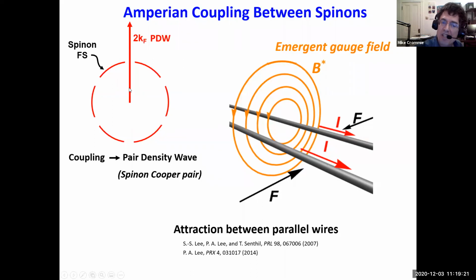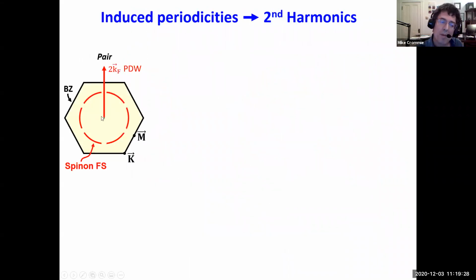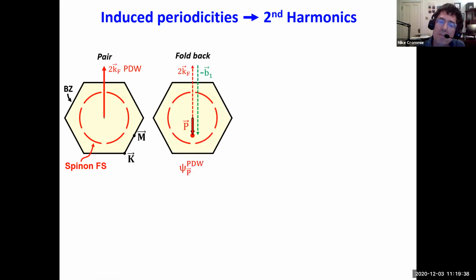So the momentum of the pair density wave is 2kF because there are two spinons there. That's a pretty big momentum, and it takes you right out of the first Brillouin zone. But we can fold the pair density wave back into the Brillouin zone by simply adding a reciprocal lattice vector of the CDW lattice. If we fold back into the Brillouin zone, we get this little red vector called P. That stands for primary, and that's the crystal momentum of the pair density wave in the Brillouin zone.